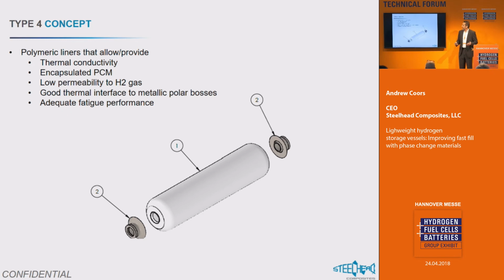So our concept here, and we're hoping to do it over the next few years, this isn't a core business, this isn't just us playing around, is to use these things called dangling chain polymeric PCMs. So it's a phase change material that is actually put into the polymer matrix. And then if we rotomolded or blow molded a liner out of it, we could in theory have a much more thermally effective Type 4 plastic liner that we reinforce with the composites.